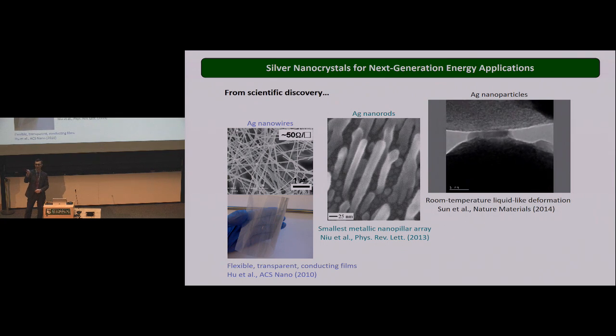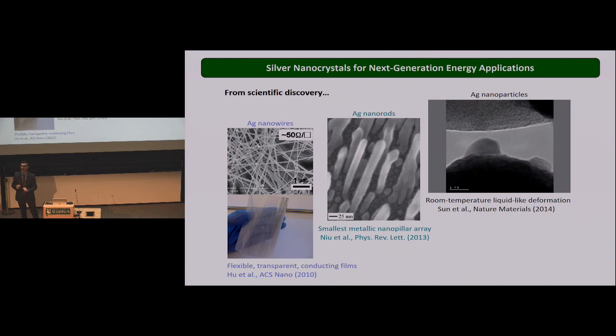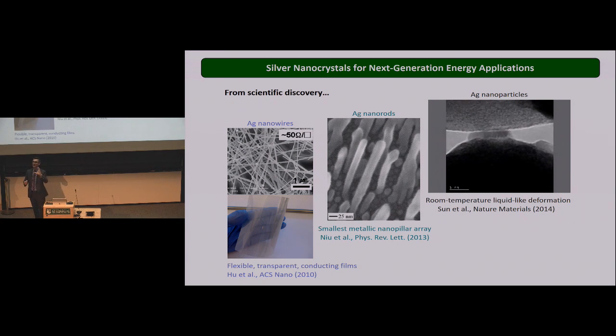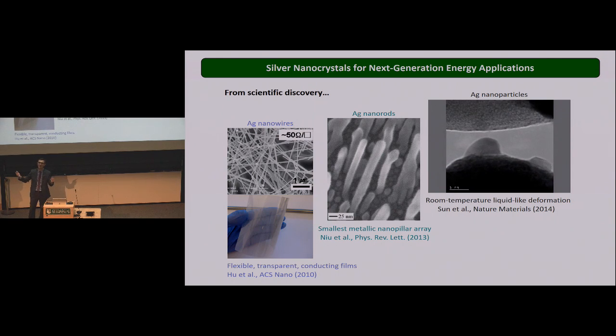So the question is about the difference in time scale between the atomistic simulation and the experiment, especially with regard to deformation mechanisms like dislocation propagation. Fortunately, dislocations travel very fast in a crystal, which is why it's very hard to see in the experiment. You don't really see the dislocation. You see some contrast. But there's no way with current technology to capture the event of nucleation and propagation within an ultra-thin nanowire. In atomistic simulation, the benefit is we can take snapshots on the order of picoseconds, right? We can take 1,000 snapshots within 1 nanosecond, and typically your dislocation nucleates, propagates, and disappears on the other surface in maybe 5 picoseconds, right? But we can capture that in the simulation.